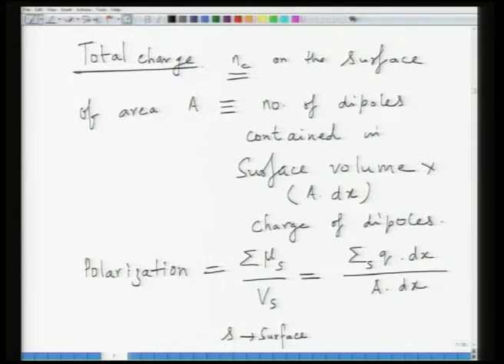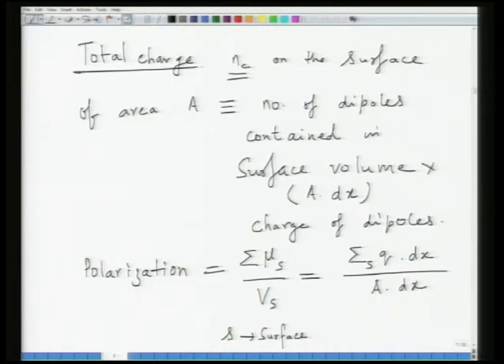So, is that clear? Polarization on the surface: because there is no charge inside the material, charges only exist on the surface of the material because of non-cancellation, or because of nothing existing to cancel them on the surface, and they move out by a little distance because of the application of an electric field. As a result, you create surface polarization. So, assuming homogeneous distribution of charges, surface polarization is the sum of total dipole moment on the surface divided by the total volume on the surface. So, this is your polarization P.